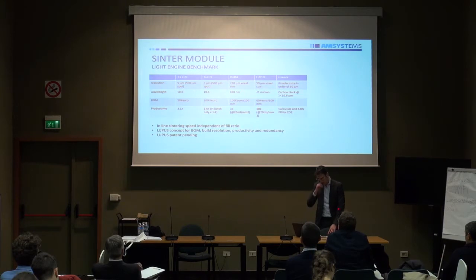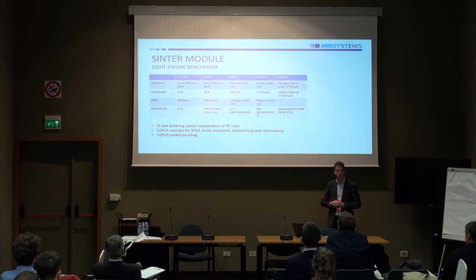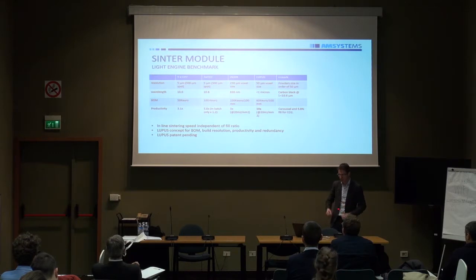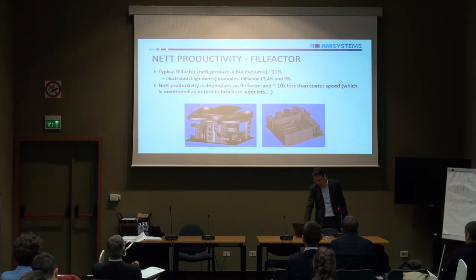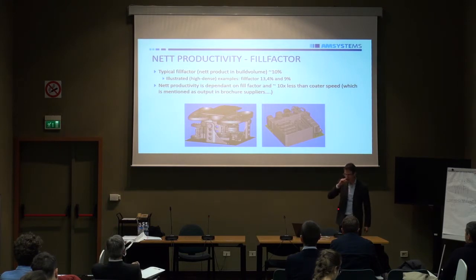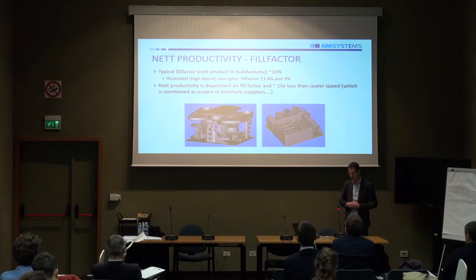But what you maybe typically see with these line arrays is that you go to another wavelength, and CO2 lasers, they have a wavelength of about 10 micrometers that absorbs in polymers very well. These low wavelengths do not absorb, almost not absorb in polymers, so you have to add absorbents. What is an important aspect for this comparison between this line array and this CO2 laser is the fill ratio, and I will explain why this is a really important part.